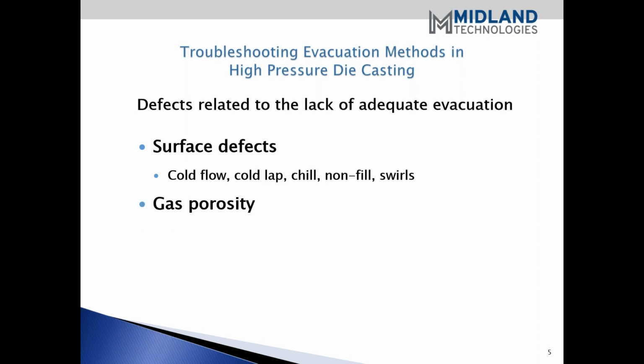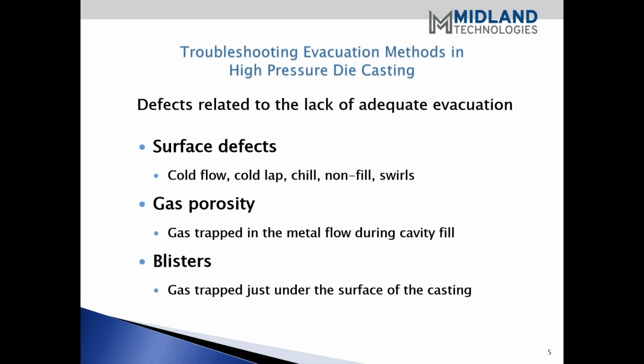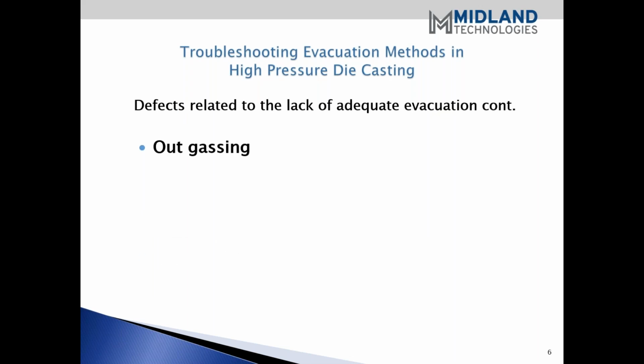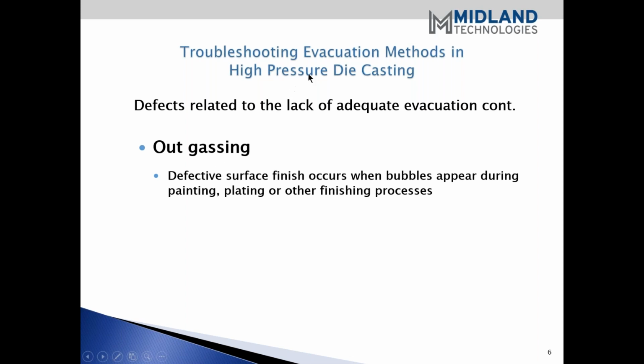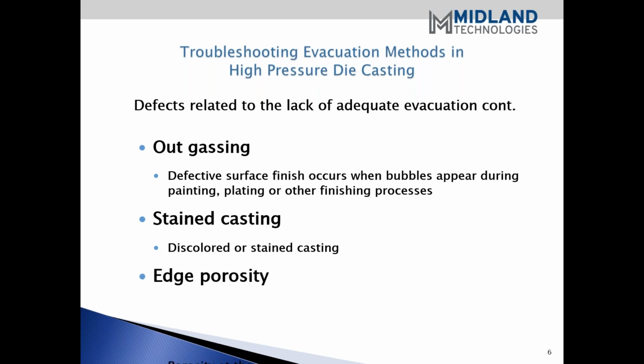Excellent. And then we also have gas porosity, which is very common. We all know that the gas is trapped in the metal flow when the cavity is being filled. And blisters can also be developed. Blisters are gases that are trapped under the surface of the casting. And then we also have outgassing. A defective surface finish occurs when bubbles appear during painting, plating, or other finishing processes. And there's stain casting, which is a discoloration of the casting, and edge porosity, which is the coarse porosity at the gate.